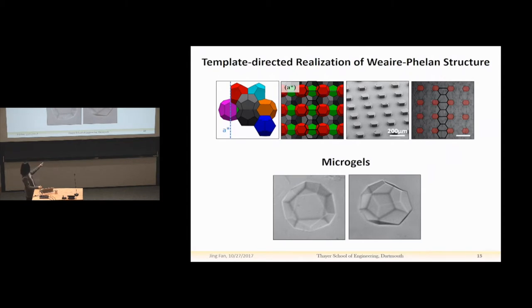So this results in the 2 shaped microgels like this, which is exactly the 2 units that we saw from the Weaire-Phelan structure. We call it template-directed droplet crystallization. It's very similar to colloidal epitaxy, when we have the layer-by-layer growth of oriented crystal structure. Even though the structure is slightly out of equilibrium, because it has a relatively low energy, we can still get it.